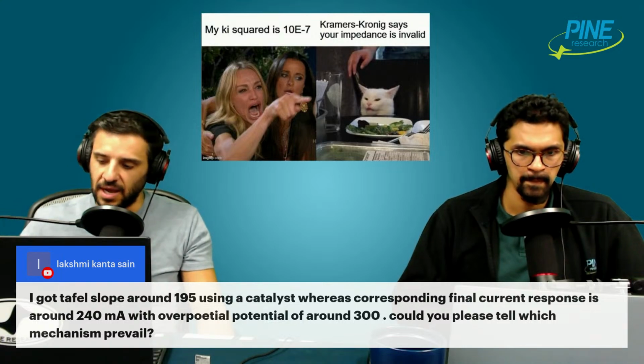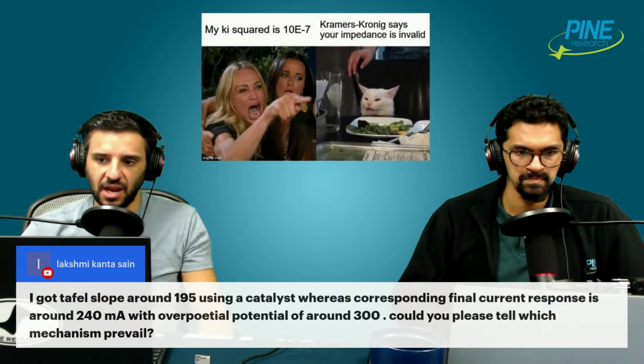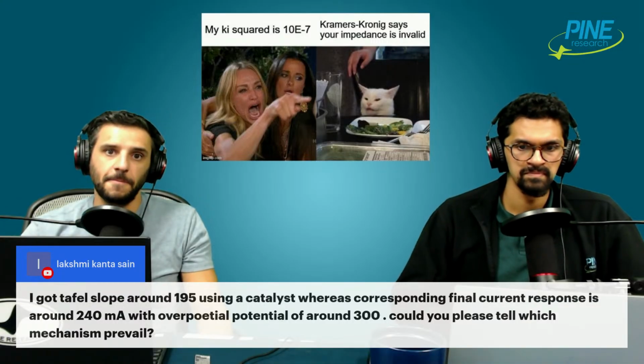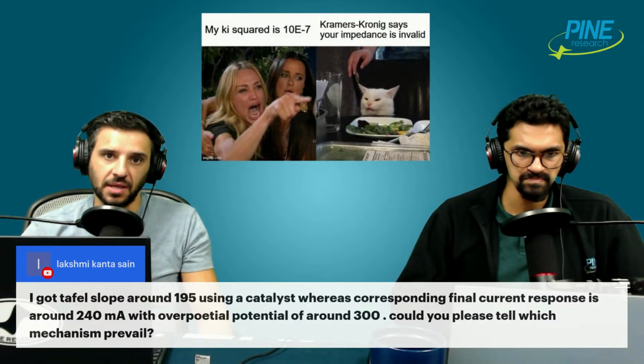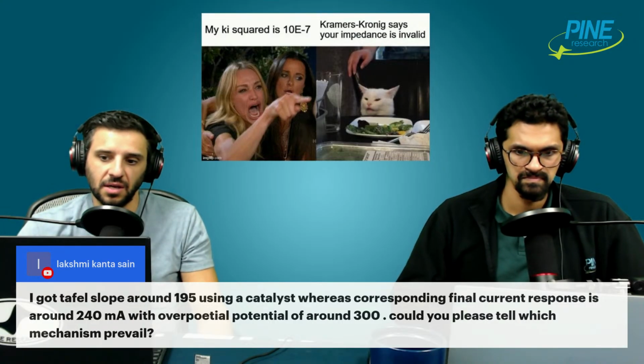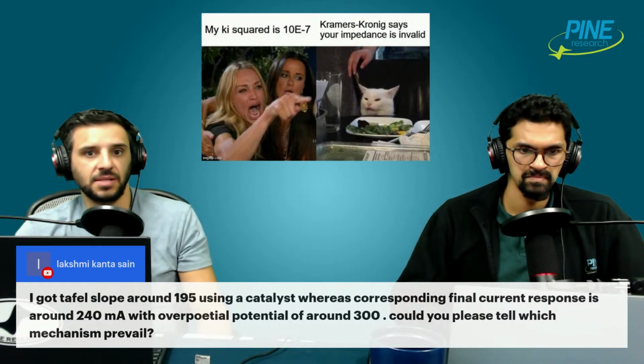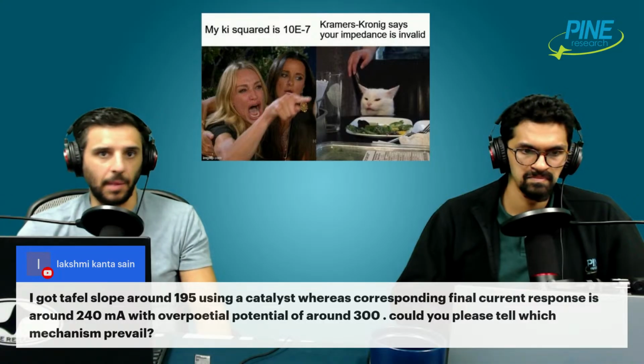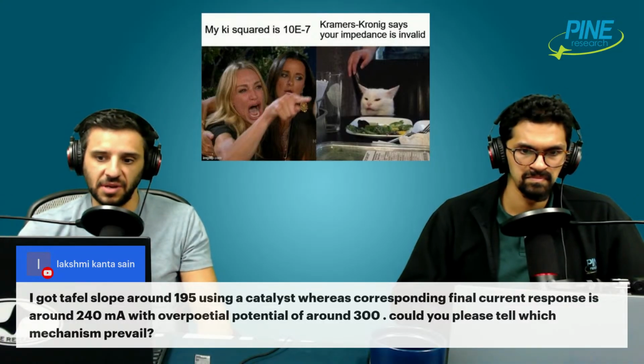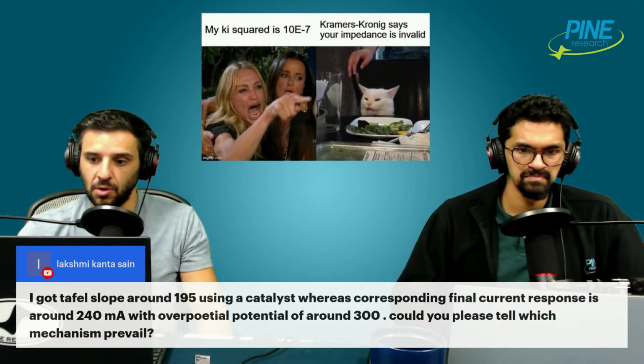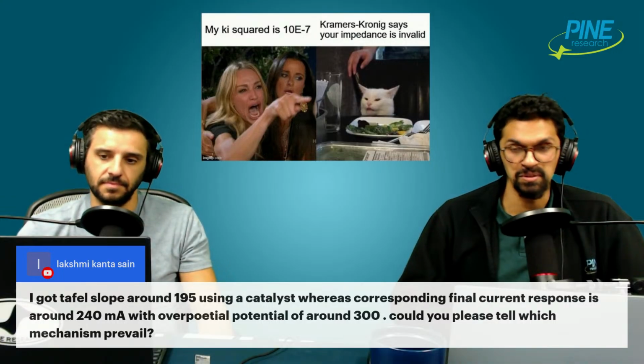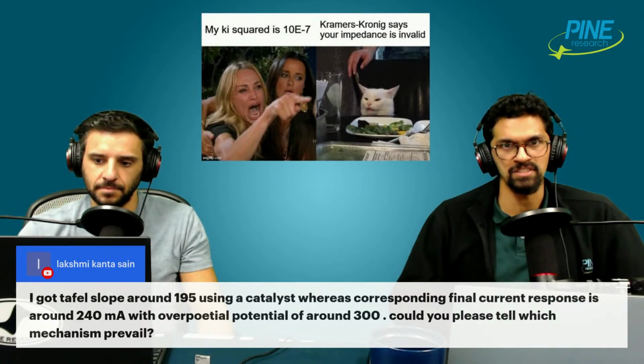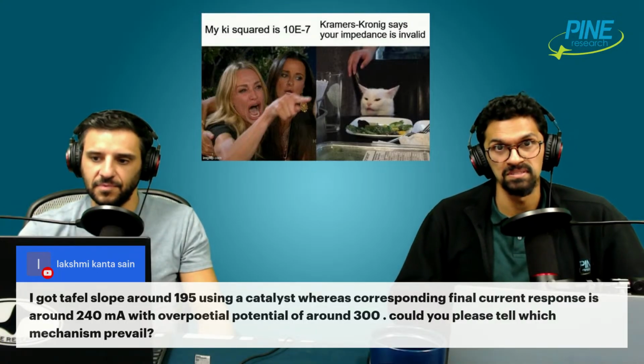So I would encourage you to be very careful and clear about your data and make sure that if you're making a Tafel plot, it means something, because you probably have current and voltage data that is convoluted with capacitance and mass transport and maybe even hydrogen bubbles messing up stuff. And you got a lot of contributing factors such that your current data is not just kinetics. Very probably. So the Tafel slope you got tells you nothing about your mechanism. Yeah, because you can't have sub 1 electron transfer, right? Especially for HER.